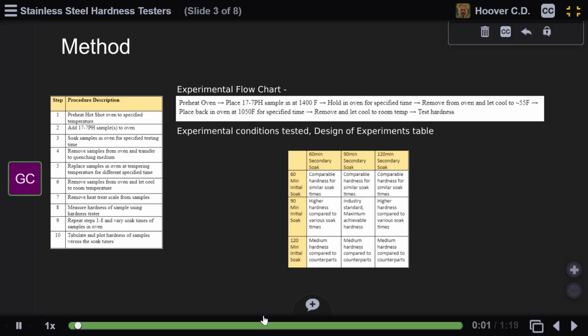In terms of our methods for this experiment, seen through both the table and the experimental flow chart on this slide, the first step is to preheat the oven to a specified temperature. After it reaches that point, I add the 17-7 to the oven and soak the samples for a specified testing time based on research we did. After that time, remove it from the oven and transfer to a quenching medium. For this experiment, we determined air to be the best medium, and let it sit out for about an hour or so.